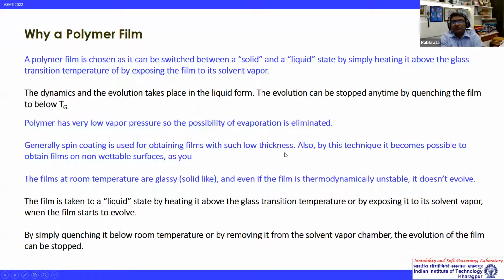So there are certain details I have written. Generally, spin coating is used for obtaining films of such low thickness. Also, by this technique, it becomes possible to obtain films on non-wettable surfaces. Films at room temperature are glassy, which are solid-like, and even if the film is thermodynamically unstable, nothing will happen. When the film is taken to the liquid state by heating above the glass transition temperature or exposing it to its solvent vapor, it starts to evolve.